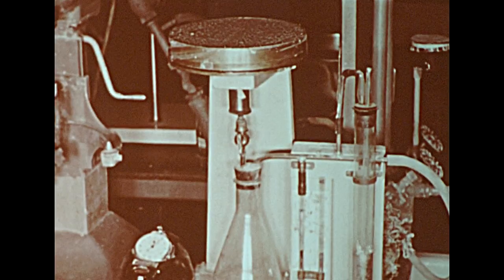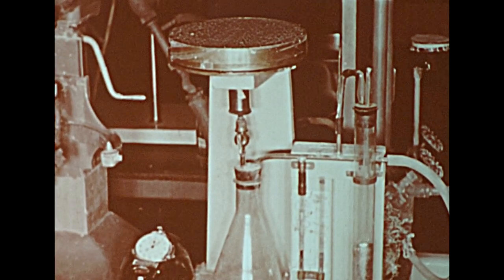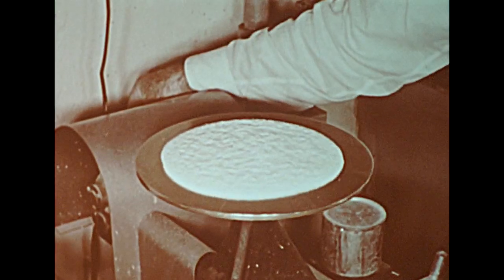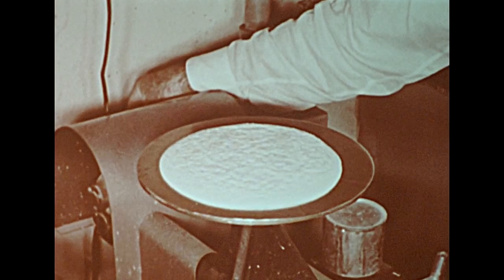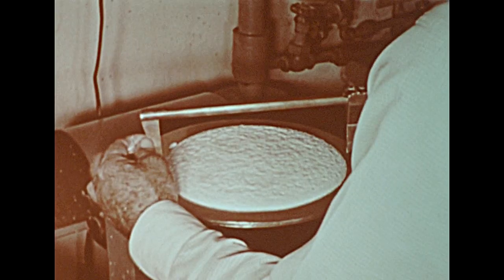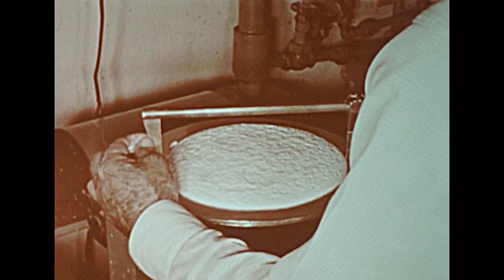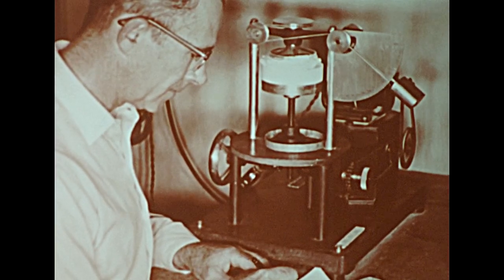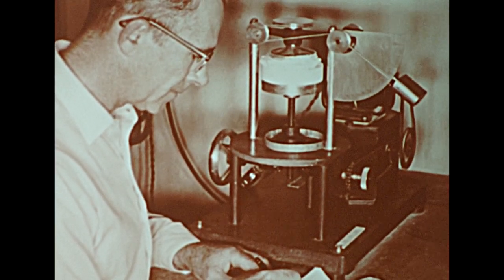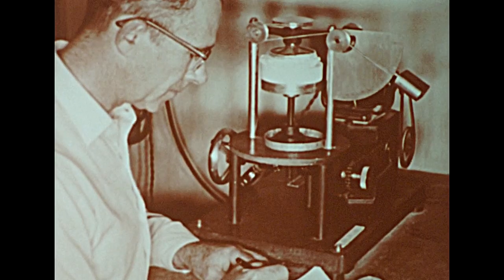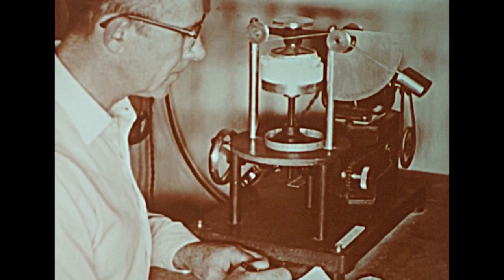The mortar is then placed in a suction device for 1 minute, after which the flow is measured again. This time, the flow is not much less, 99. The water retention value is 99 divided by 105, or 94%.